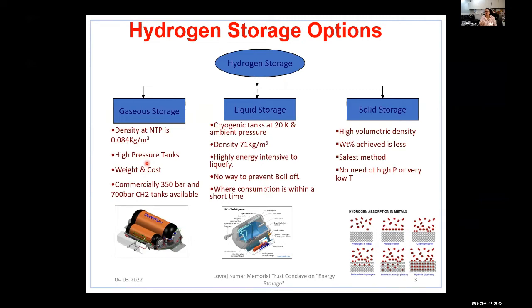At the same time, when it is such a high pressure, safety remains a concern. The other option could be you cool it down to 20K and then make it into liquid. So the density improves considerably. We can see that in these numbers. But then the process of cooling it down or making it liquid hydrogen is highly energy intensive. It takes up about 30 to 40% of the energy content of hydrogen.